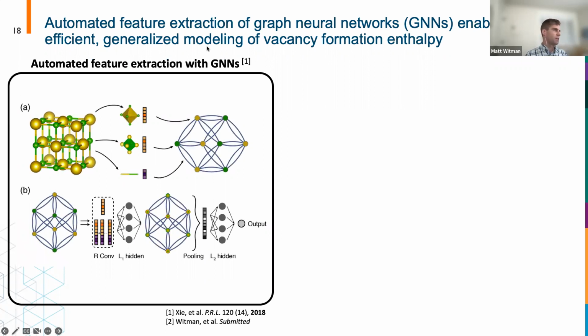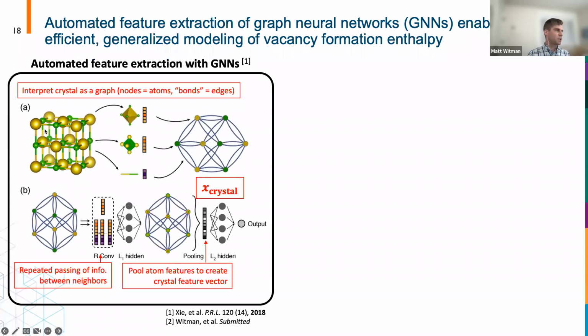So to quickly go over what GNNs are, the power of GNNs is that you basically take a crystal structure and you can interpret the nodes as atoms and the bonds as edges. And then once you concatenate the information between neighboring nodes and edges and pass them through a feed-forward neural network layer, you provide an update after each convolution to the feature vector that's on each node. Once you pool that information all together in some kind of pooling operation, like a sum or an average, you end up with this feature vector X_crystal that is representative of your material. And then once you apply any final feed-forward layers, you can predict some kind of target property of interest.